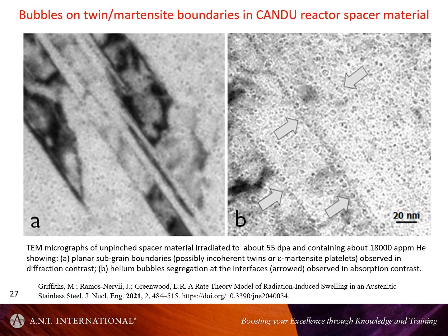Just to again finish off on that theme, one of the things that Puyen was interested in was whether you're getting segregation along these platelets of cavities. It turns out that even in the neutron irradiated case, transgranular fracture, when it's observed, and it is observed in a small number of cases, it can certainly be associated with the segregation of cavities along the interface. So here's some twins or something like that. I don't think there was any detailed study here performed,